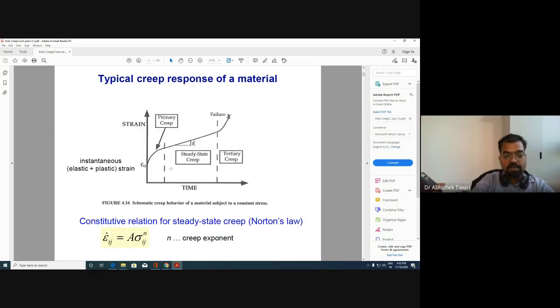So for example, this is the response of strain versus time at a certain amount of stress. Let's say that amount of stress is 100 megapascal at some temperature. If you increase the stress from 100 megapascal to 400 megapascal, this behavior will change. The strain change with time will be very drastic because you have increased the stress. What can happen is, the primary creep part will be very small. It can be suppressed, and so you will have only the steady state creep and then tertiary creep.